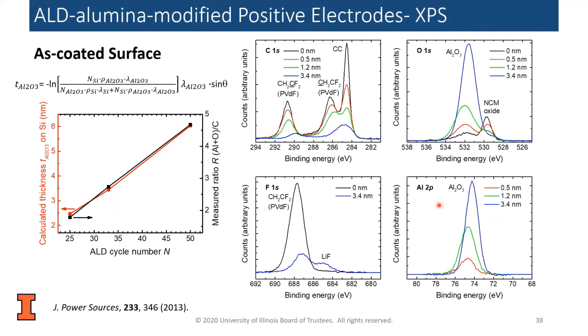They're very rough and sort of like a mountainous type surface to the electrodes. And so what we did is we developed a method where, during our ALD deposition, we would co-deposit together with our cathode. We'd put a silicon wafer next to it, and then we'll get a nice planar surface, and then we'll pull those both out and do some analysis. And so what we'll do is we look for a signal that we could relate to the thickness on the silicon wafer.